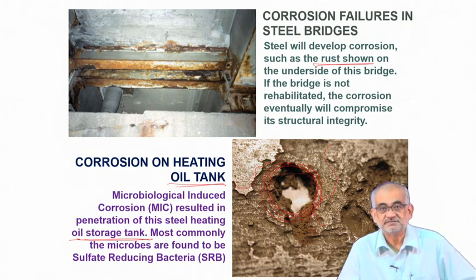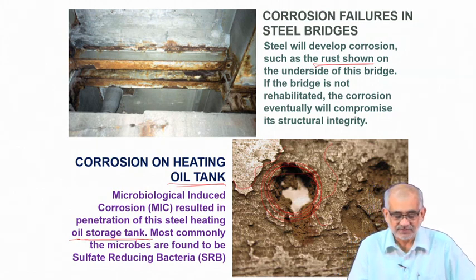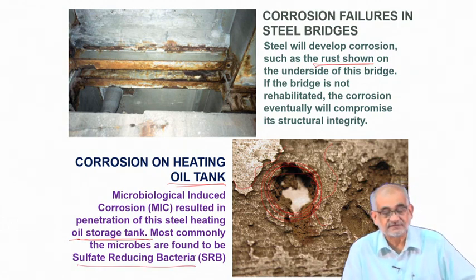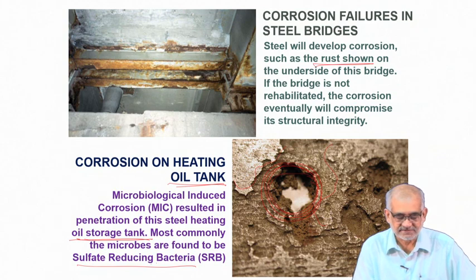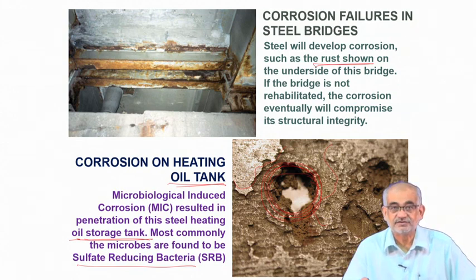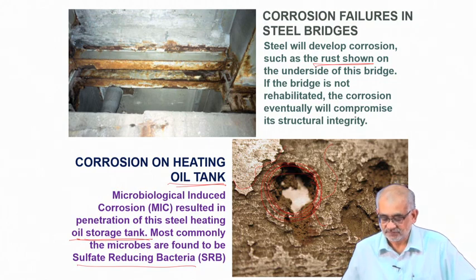There is no escape from it, because you actually have to have petroleum, and in order to store it you need metallic vessels, and the petroleum will contain a lot of sulfide or sulfur-containing fluid, and there are bacteria called sulfate reducing bacteria which will feed on such stock, and in the process will cause such corrosion, even form such holes.